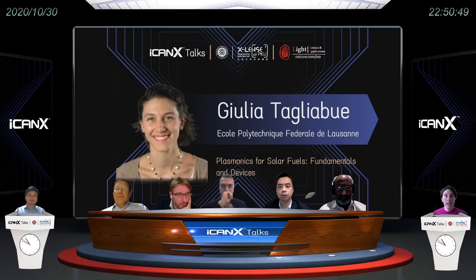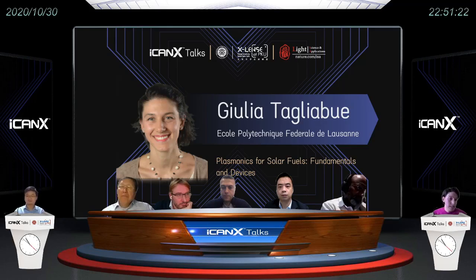Not exactly in terms of the overall behavior. So I would expect that we would still observe a very fast rise of the signal and a relatively longer decay on the nanosecond time scale. Definitely, it's going to impact the efficiency of the extraction, because depending on the photon energy at which we have the resonance, we can have higher or lower energy of the carriers compared to the Schottky barrier. And so if we go too long of a wavelength, we will basically not be able to transfer carriers for that reason. So that is definitely going to be visible in the signature, but not so much in terms of the other types of properties of the signal that we see. I'm not sure if I completely answered your question.